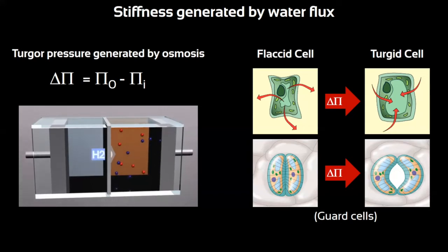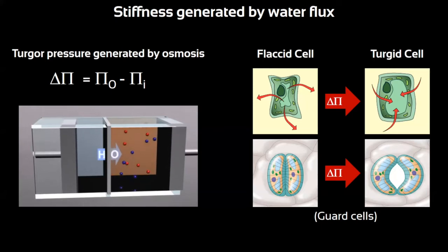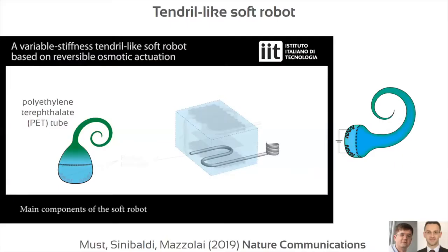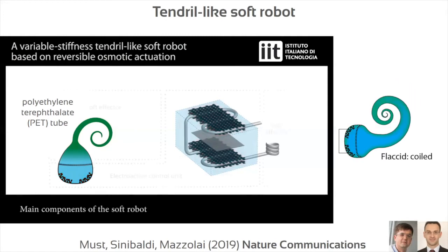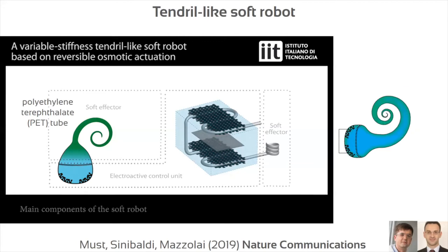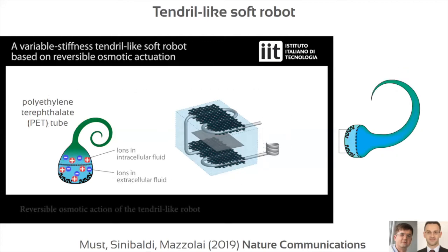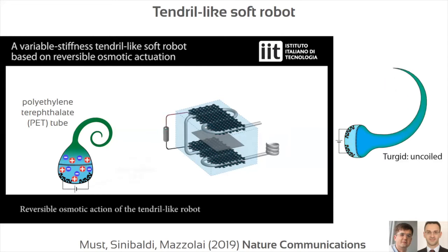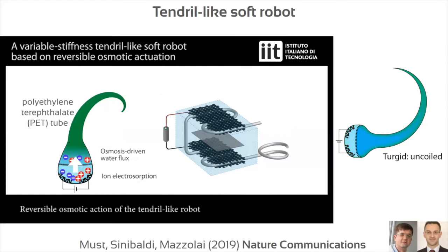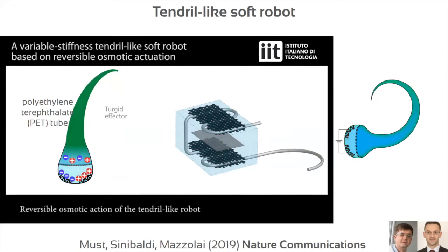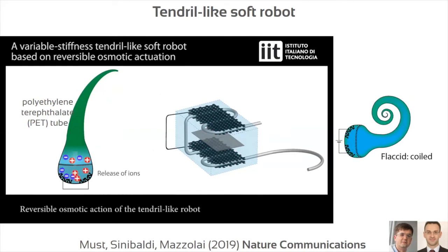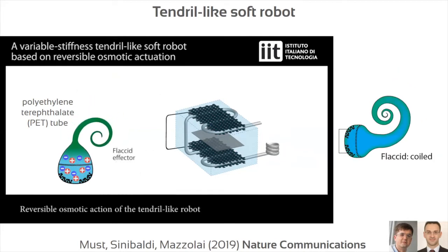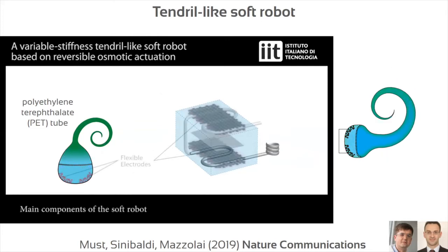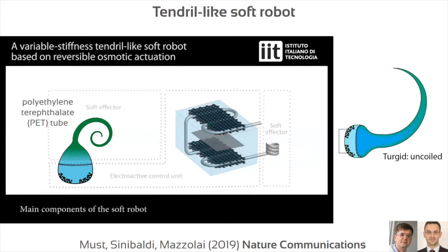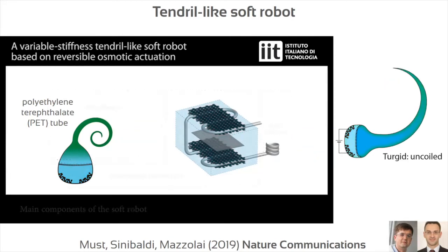And so we developed several osmotic actuators, but I would like to show one of the last prototypes that we have developed based on this concept. Again, we started from a climbing plant. The tendril is one of the systems used by climbing plants to anchor to external supports. And what we developed is a completely soft robot based on PET material, in which we put soft electrodes based on carbon fibers and an osmotic membrane. We can apply a low voltage to the system to absorb and desorb ions and to have a consequent movement of water inside the soft arm. And this is the way in which we can increase the stiffness.